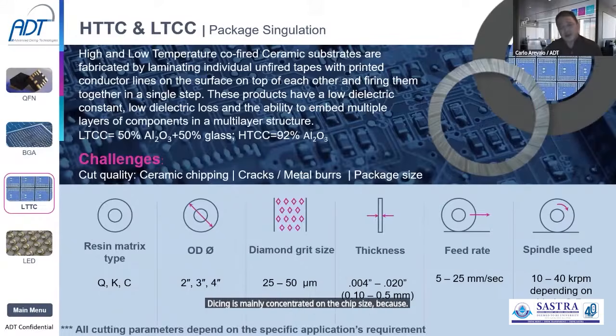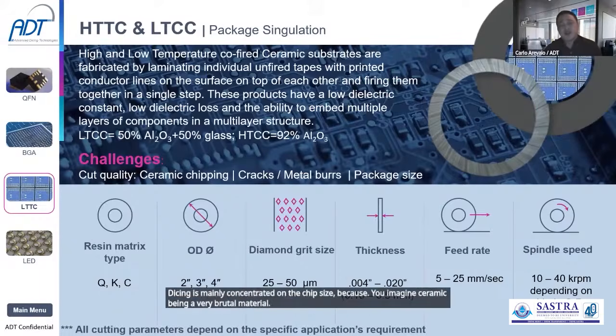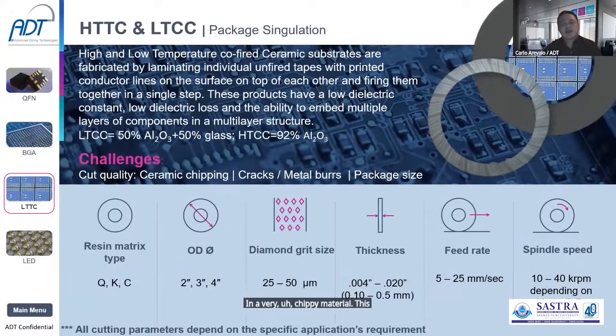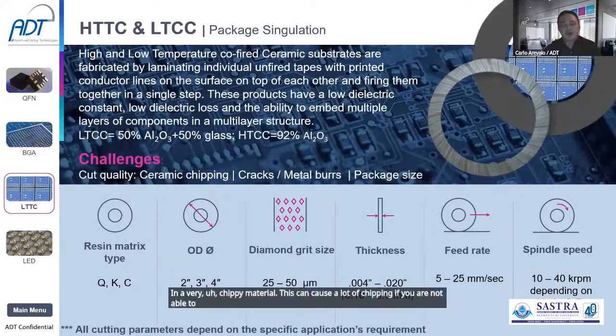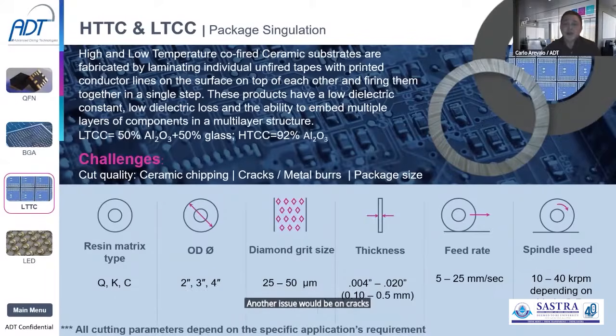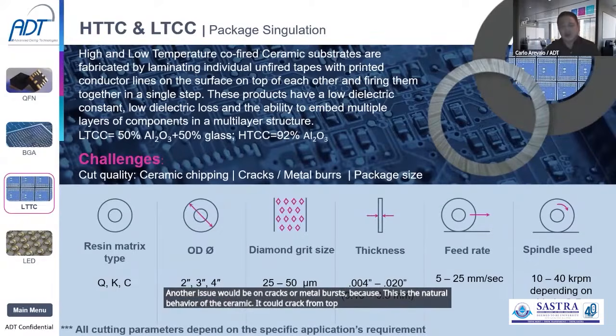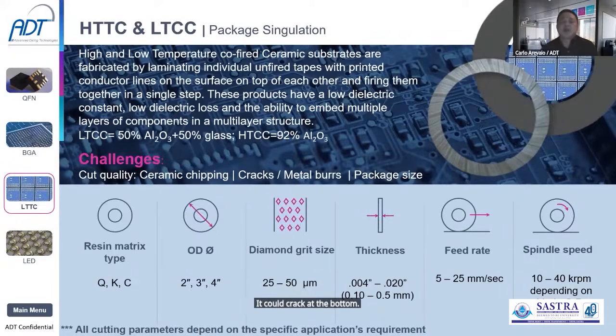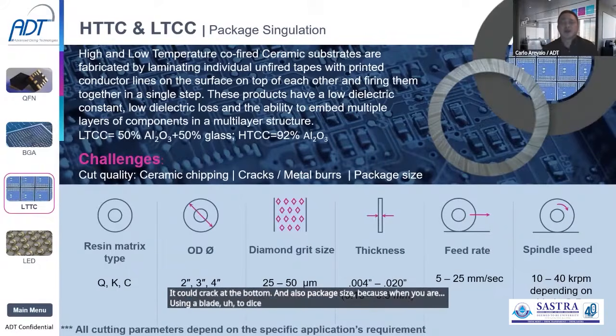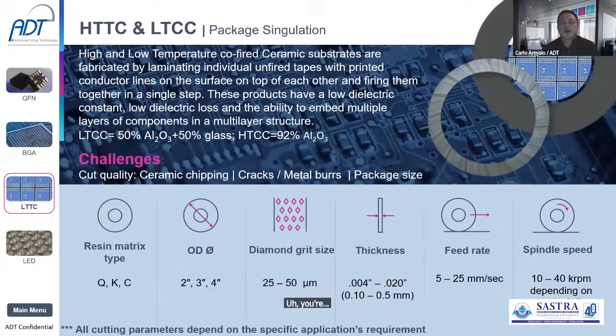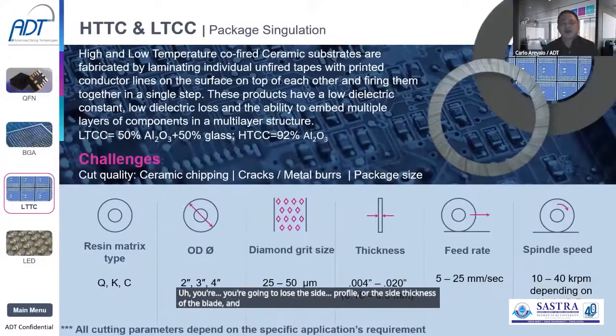The challenges for this particular ceramic dicing are mainly concentrated on chip size, because ceramic is a very brittle and chippy material. This can cause a lot of chipping if you are not able to optimize your blade parameters or your process parameters. Another issue is cracks or metal burrs, because this is the natural behavior of the ceramic. It could crack from the top, and also at the bottom. And also package size, because when you are using a blade to dice a hard material, you're going to lose the side profile or the side thickness of the blade, and it can create an odd shape, and this can cause failure in the package size.